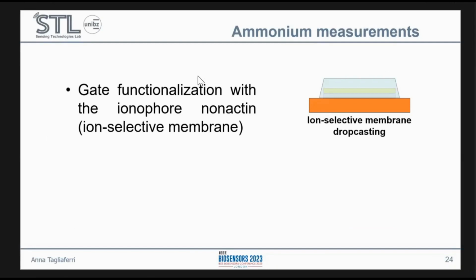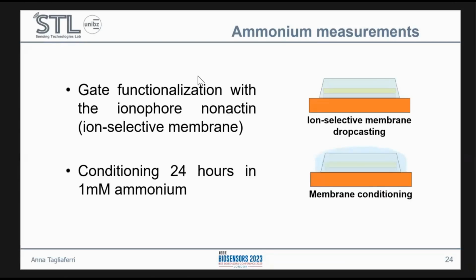Of course, we had to validate this with some measurement of some analyte. We chose as proof of concept to measure ammonium. First, we drop casted an ion-selective membrane on our gate containing an ionophore produced by actinomycetes, that is nonactin. After this, we had to leave the device conditioning in 1 millimolar ammonium, since we had previously seen that this conditioning step was greatly improving the sensitivity of the sensor.